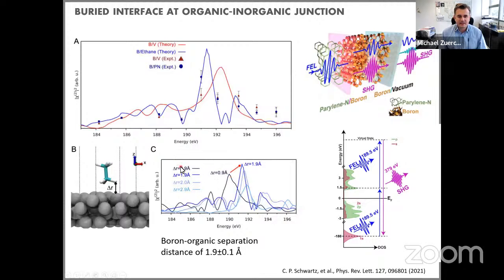If you have the organic on top of the boron, you get a slight charge displacement across the interface from boron. You can think of it that the parylene takes on a little bit of the charge cloud from the boron, and that causes the states at the edge to shift, such that you get a slightly different transition energy for boron at the interface. And that's what you effectively probe with the second harmonic. If you measure the XAS spectrum of those systems, as we showed in our paper, you see absolutely no difference between boron vacuum versus boron with parylene, because you basically measure bulk. But if you measure second harmonic, you actually see a spectral shift. And the simulations confirm it.